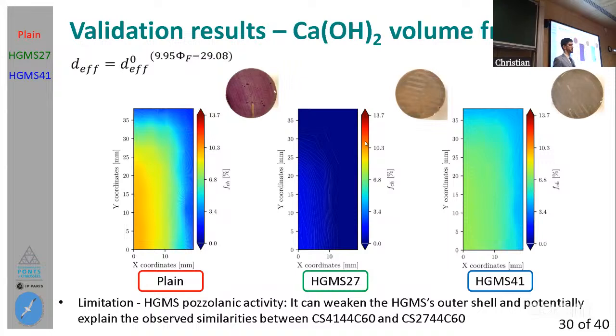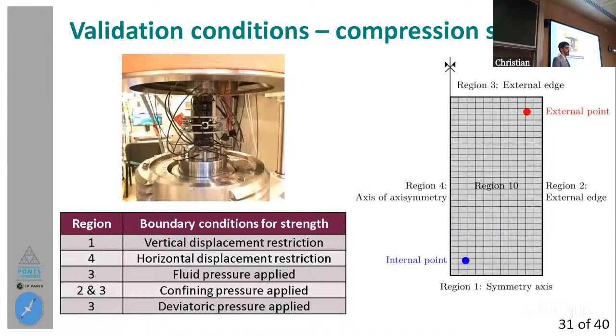But it is worth mentioning that we are having some interesting results for cement paste with HGMS41. There you will see that we have a pattern of colors more or less similar to that presented in the plain cement paste. In fact, we have even less consumption of the calcium hydroxide. And this could be related, and will be discussed a bit more later, to not being able to break the spheres, because the input data is the result that we have from MIP on HGMS powder samples. So with those results, 20 megapascals doesn't reach the breaking pressure. So the spheres are not being broken, and this parameter is not being affected. So that's it. Let's see what we obtain from the compressive strength.